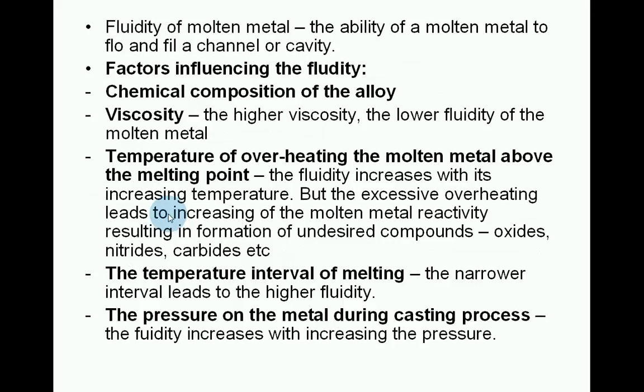Fluidity of a molten metal is the ability of a molten metal to flow and fill a channel or cavity. The factors influencing fluidity include the chemical composition of the alloy, viscosity (the higher the viscosity, the lower the fluidity), and the temperature of overheating the molten metal above the melting point (fluidity increases with increasing temperature, but excessive overheating leads to increasing reactivity, resulting in the formation of undesired compounds such as oxides, nitrides and carbides). The temperature interval of melting — a narrower interval leads to higher fluidity — and the pressure on the metal during casting also affect fluidity; fluidity increases with increasing pressure.